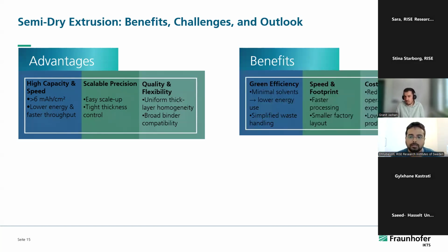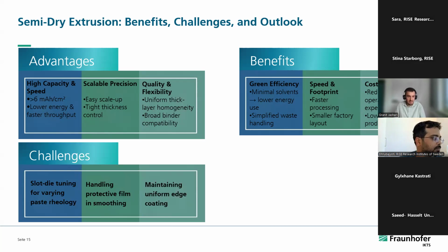The quality is still a uniform layer across the whole width of the slot die. The benefits: we are using really minimal solvent, and it's faster processing with reduced operating expenses, which means the cost investment is not that high compared to tape casting. Since in this case it's not necessary to have all the drying and the recovery of large amounts of NMP.